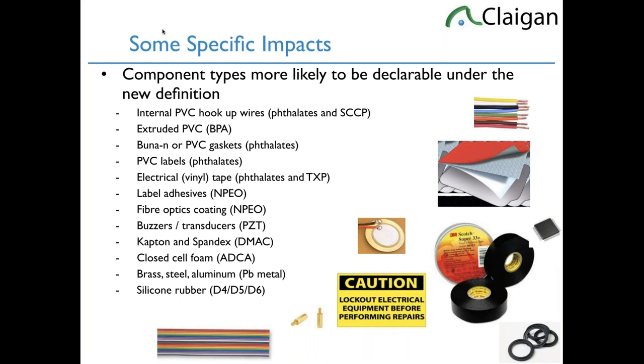Something we're looking into. One of the two newer sets of SVHCs are super common: lead in metals. So lead in brass, lead in steel, lead in aluminum, which are all allowed under RoHS to certain levels. But they'll be above 0.1% by weight very commonly. They're not banned. You just have to declare them. As long as you meet, in electronics, the RoHS exemption, you can have lead up to the allowed percentage for each material. But it's declarable.